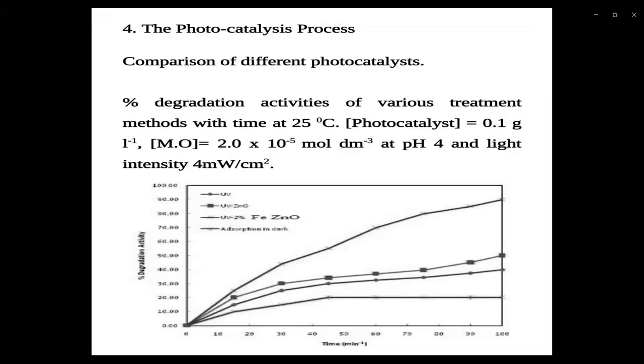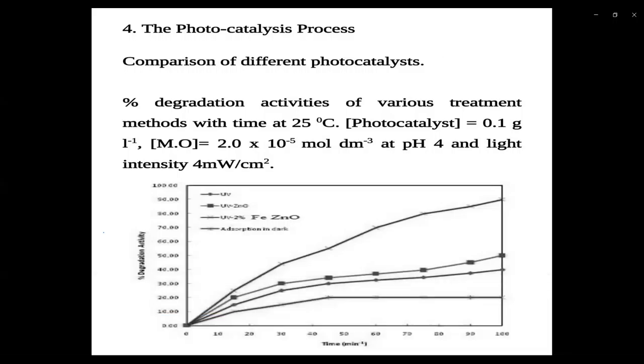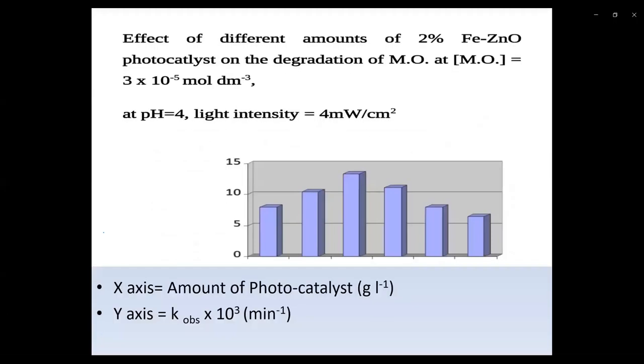So this slide shows the photocatalytic degradation of methyl orange at pH 4. The different peaks are observed here. With the FeZnO particles acting as a catalyst, more degradation takes place. So the highest peak it shows compared to UV, ZnO and only ZnO, but the 2% FeZnO has more efficiency in the photocatalytic degradation process. The 2% FeZnO photocatalytic doses show the photocatalytic degradation of methyl orange.